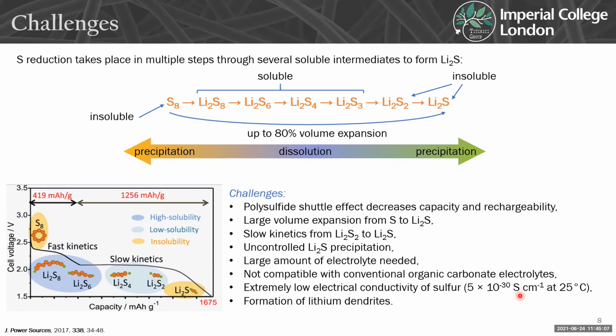Of course, one of the obvious issues is that sulfur is very non-conductive, so we need to add a conductive additive into the electrode. And then on the other side, with the lithium metal, you have the formation of lithium dendrites, which is obviously a huge safety concern.